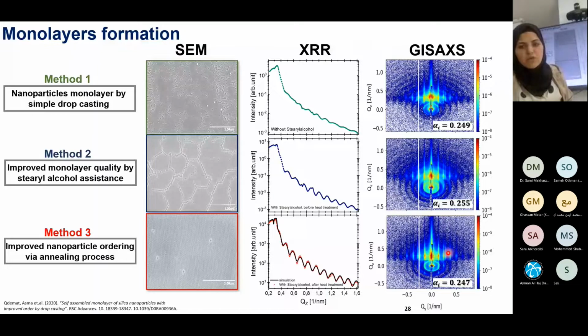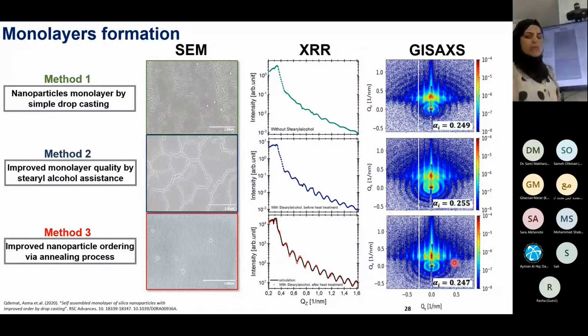where Bragg rods along the QY direction are obtained for the three patterns, which is an indication of the order of the nanoparticles. But in the monolayer obtained in method 3, these Bragg rods become more pronounced, which is an indication of the long range order. Furthermore, we observe these lines